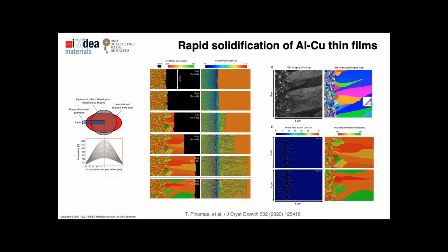However, as they mentioned in their paper, they do have some scale limitations in terms of computational time and in terms of number of grains, because they're using a multi-phase field. So there's one order parameter per grain. So in terms of memory, that can get extremely draining, extremely fast.